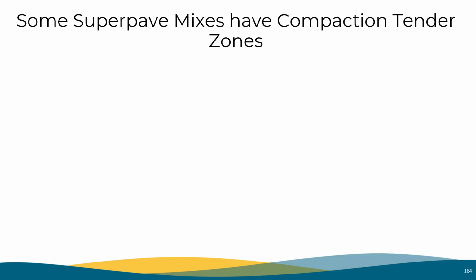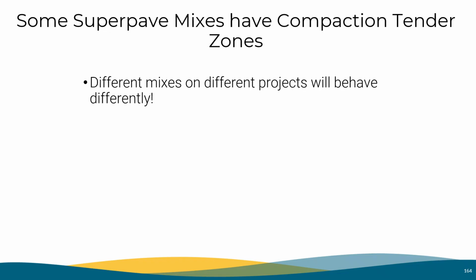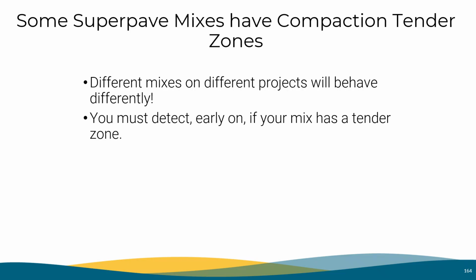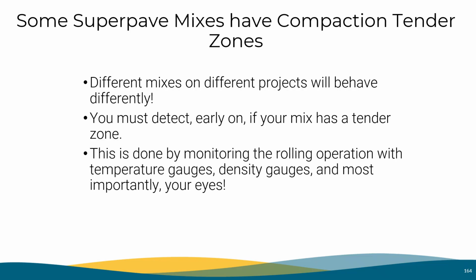And one last section I need to cover. This occurs maybe once or twice a year on a paving project. It is pretty rare, but is a possible issue that can happen. Some asphalt mixes have what we call a compaction tender zone. Different mixes on different projects will behave differently. You must detect early on if your mix has a tender zone. This is done by monitoring the rolling operation with temperature gauges, density gauges, and most importantly, your eyes.